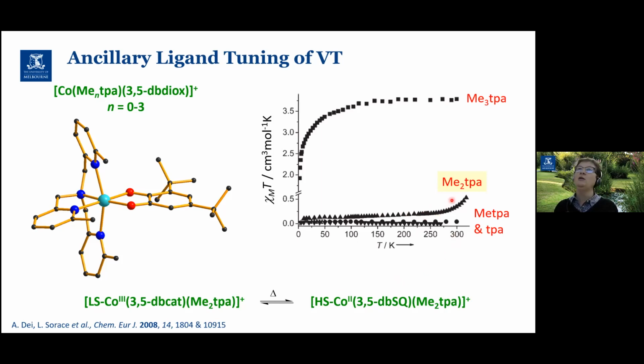So it's only when you hit the sweet spot, as we might say in English, we have 2 methyls on that TPA ligand that above room temperature or so, you start to see an uptick in your chi-T, consistent with the onset, at least, of this VT, this valence tautomeric interconversion. So essentially what's happening here really is steric control by the ancillary ligand of the cobalt-3, cobalt-2 redox potential.